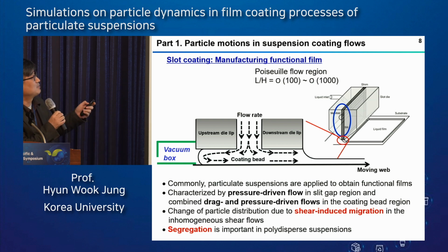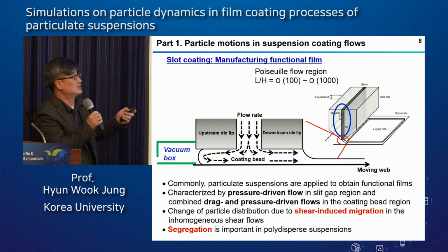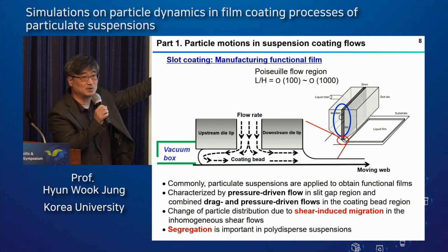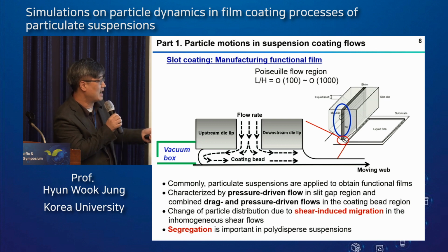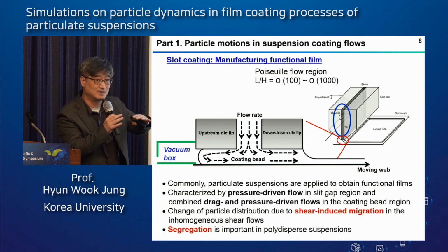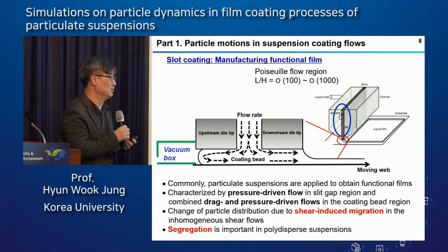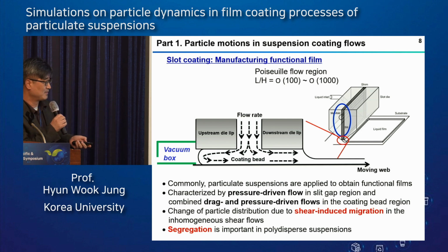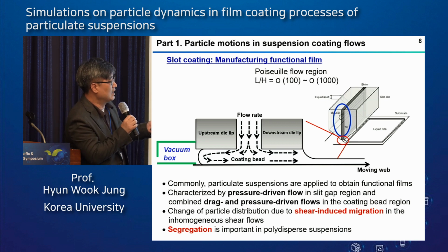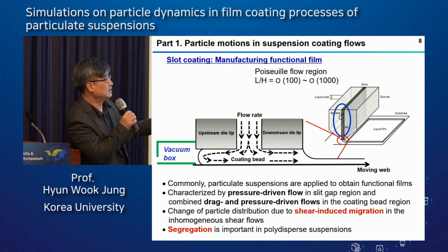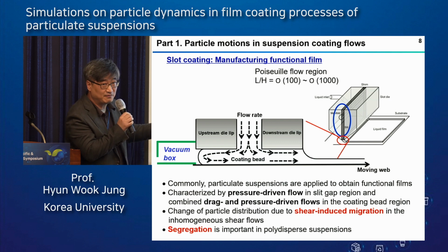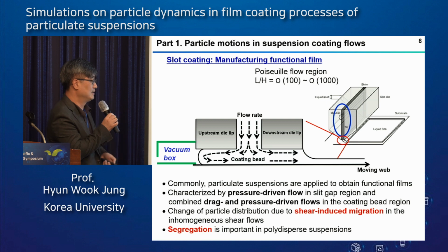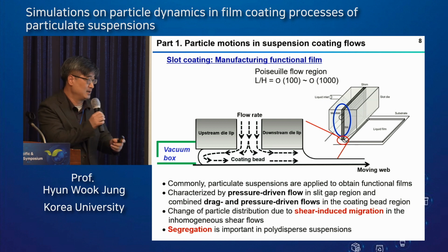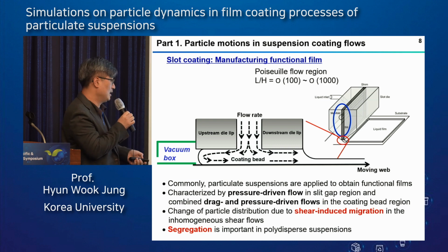So the first part is particle motion in suspension coating flows. This study was originally motivated by the slot coating processes as shown here. In general, particulate suspensions are applied to make functional films, such as lithium-ion secondary battery electrodes or fuel cell electrodes. In this slot die geometry, the coating liquid will experience pressure-driven flow, Poiseuille flow, here, and then combined drag-driven and pressure-driven flow in the very narrow coating gap region here. So particle distribution will change due to shear-induced migration in the inhomogeneous shear flow.